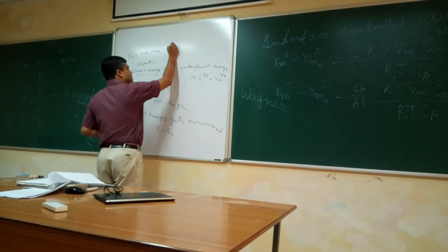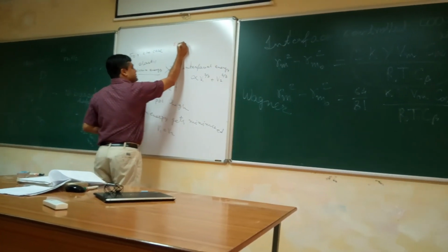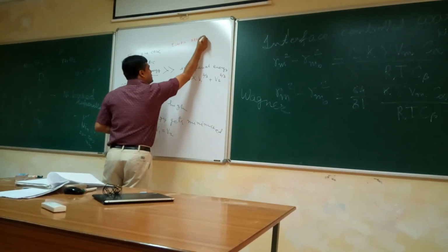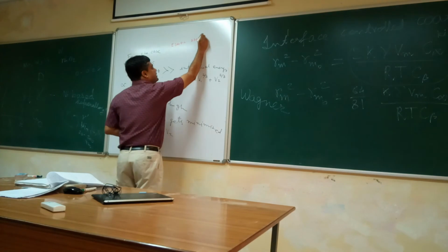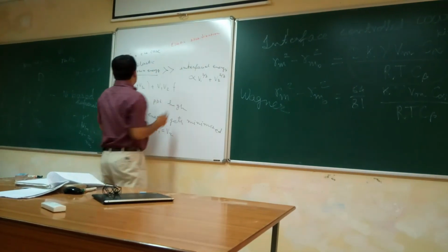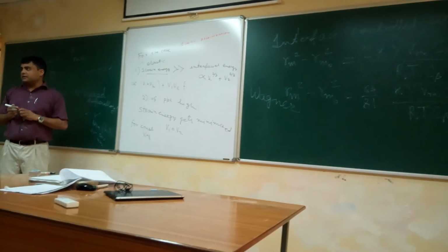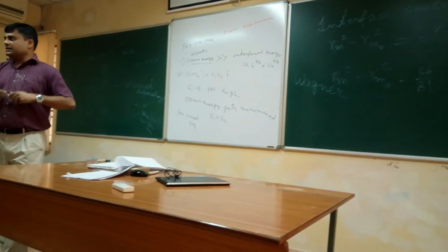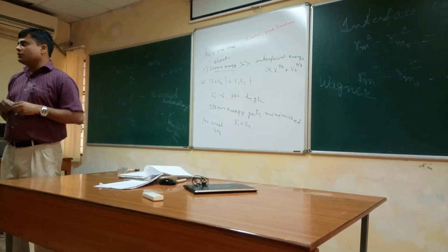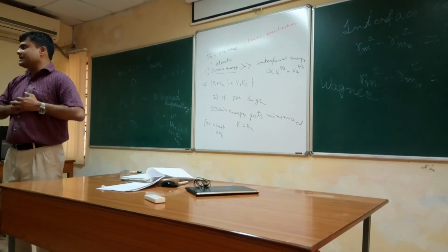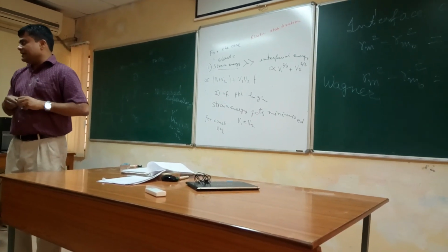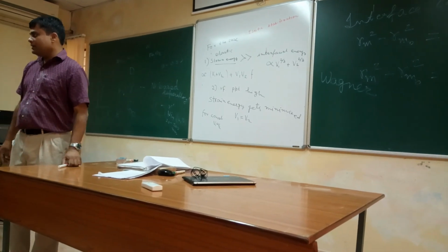This phenomenon is called elastic stabilization. It happens when the strain energy of the precipitates is much higher and the volume fraction of the precipitate is constant. It should have coarsened, but it is not coarsening because the system wants to lower the strain energy instead of the interfacial energy, because interfacial energy is lower.